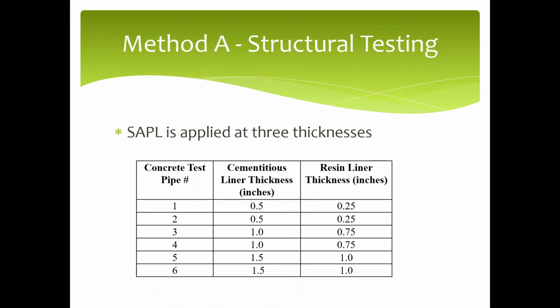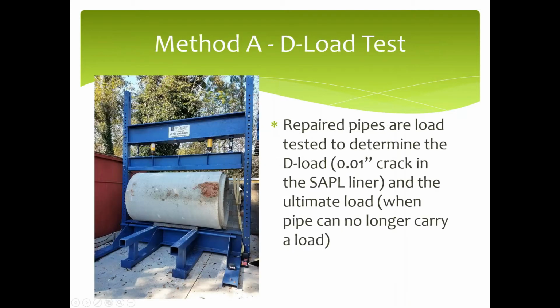He'll do this for multiple different thicknesses. We have a 1/2 inch, a 1 inch, or a 1.5 for anything that's cementitious. For a resin-based liner, we have 0.25, 0.75, and 1 inch thickness. And they'll have to do this to multiple pipes, hence we have 6. So we have 2 pipes for each of these thicknesses. So he'll apply that thickness, let it cure, and then we'll put it in this D-load machine and basically test it to D-load.